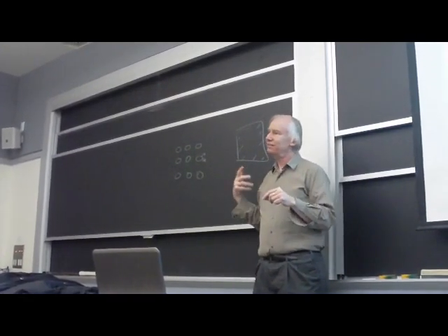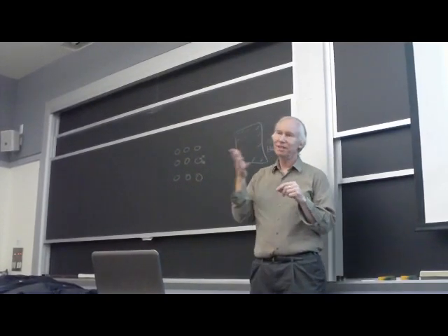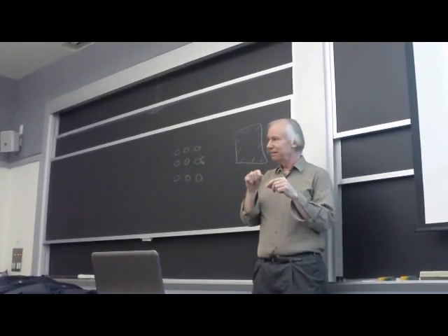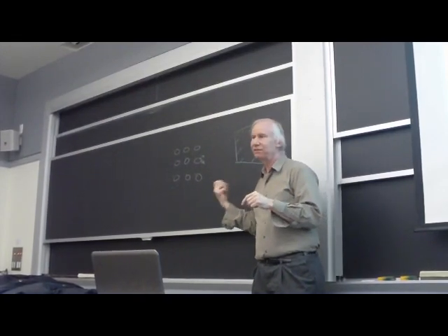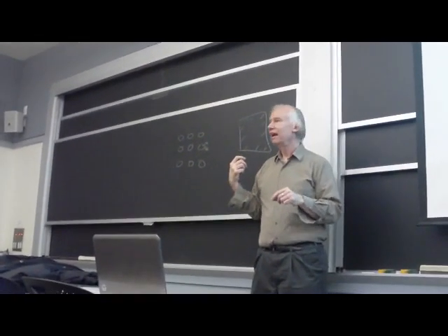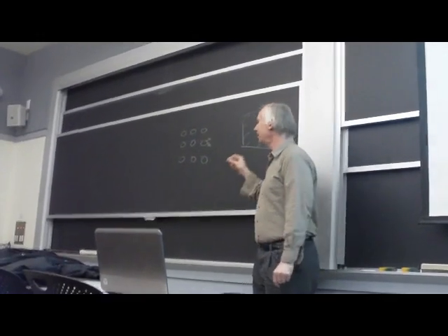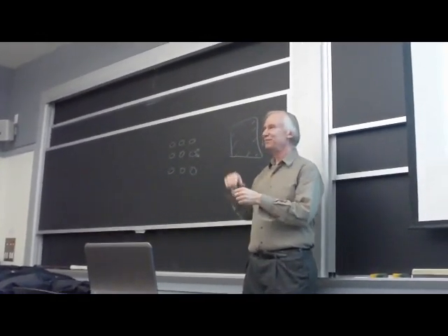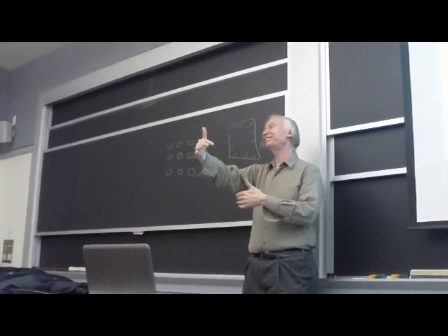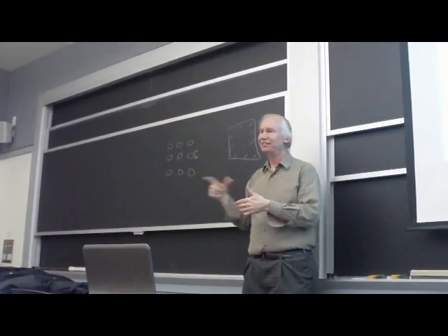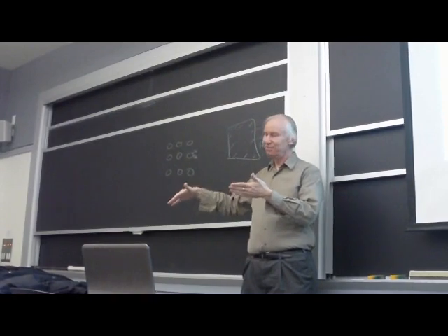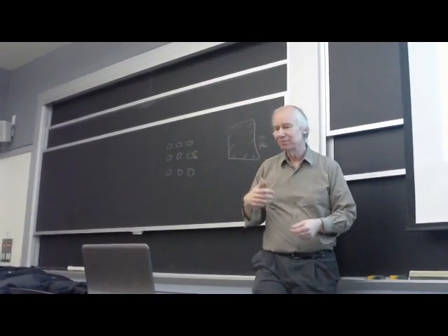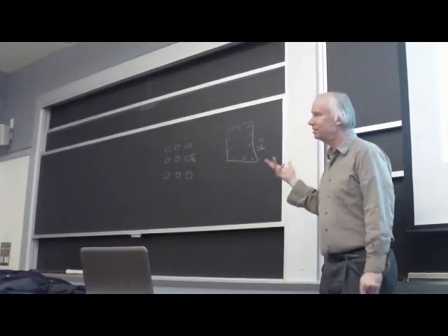So then, under the assumption that's working really well, that we're being plugged up by the helium, we would be able to see whether the dependence on diffusion size is correct. And then to back that up, we actually want a 2D set of measurements. You'd like to do it at different temperatures. With the different temperatures, you get different helium diffusion coefficients. So if you have those spatial scale and temperature, you'd be able to prove that this is what's limiting.